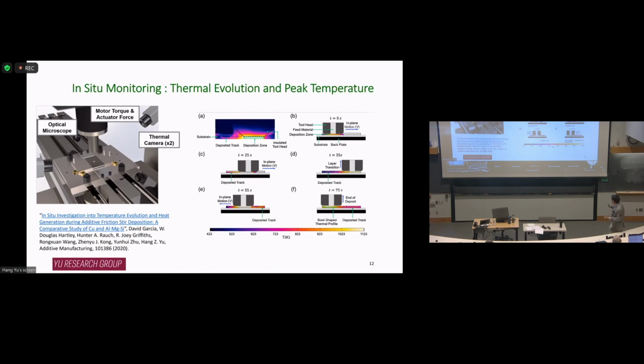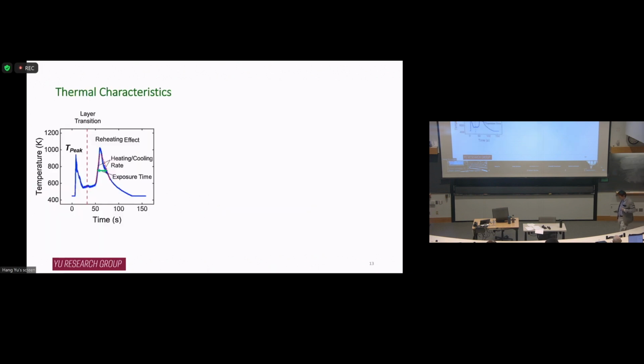Of course, you see higher temperature of the material below the tool, and for the previously deposited material, the temperature gets lower because of cooling. Right? So we did this for a bunch of conditions. Another thing we can do is, instead of looking at the entire field, we just focus on one spot and monitor temperature change as a function of time. Then we can get a plot of temperature versus time. A typical curve would look like this.